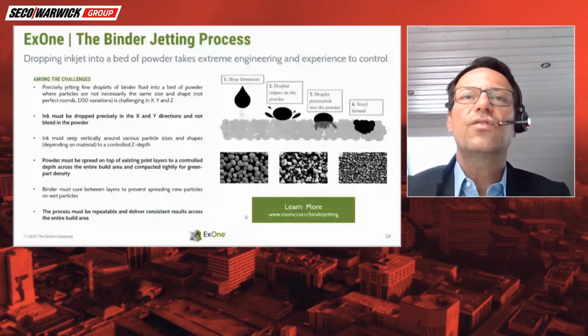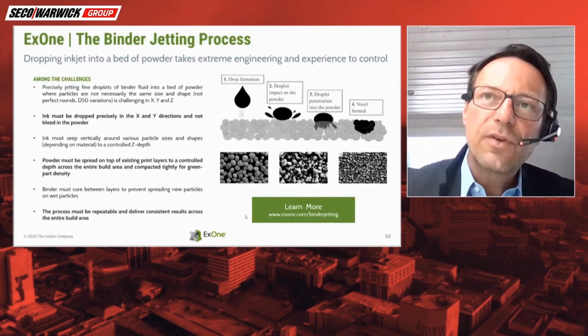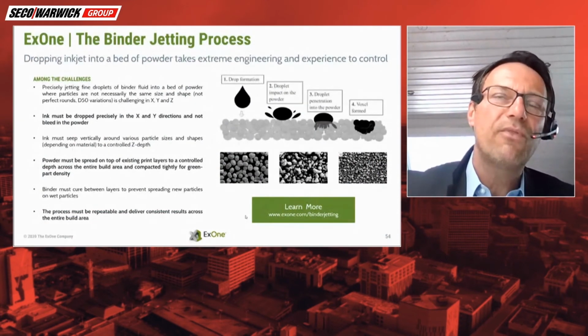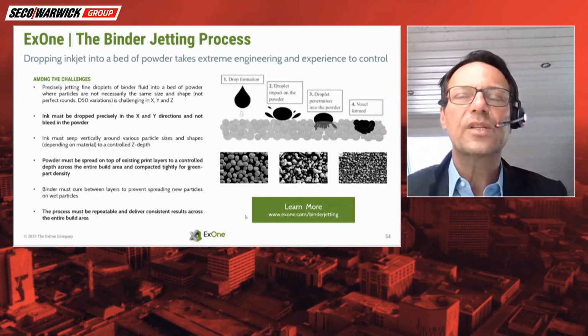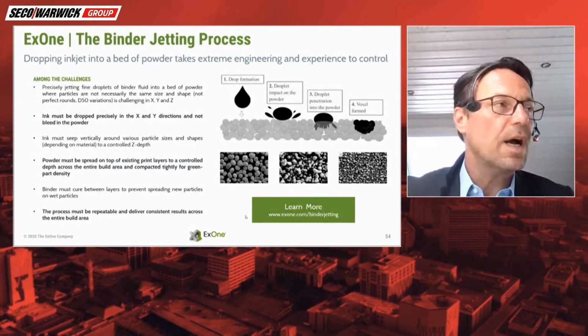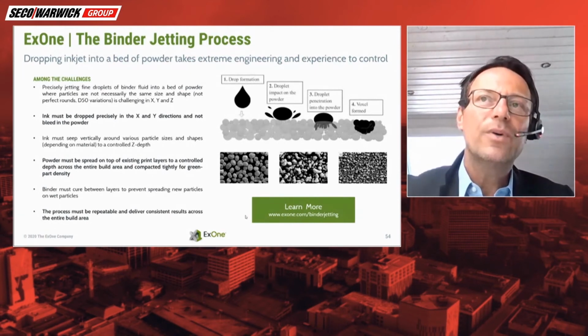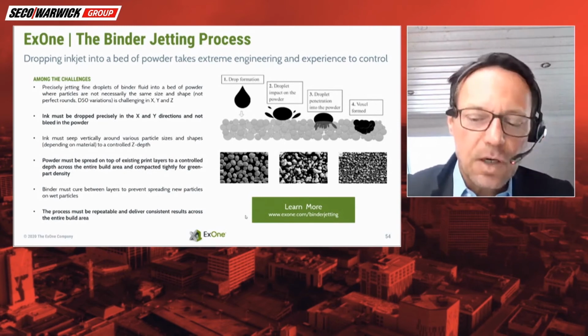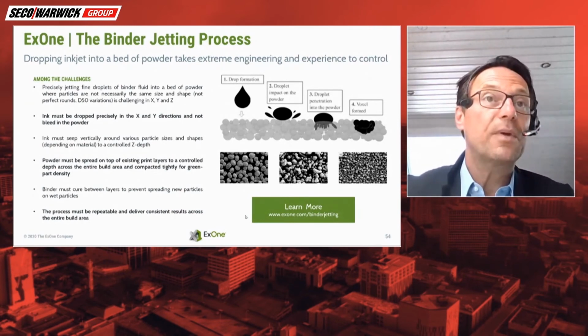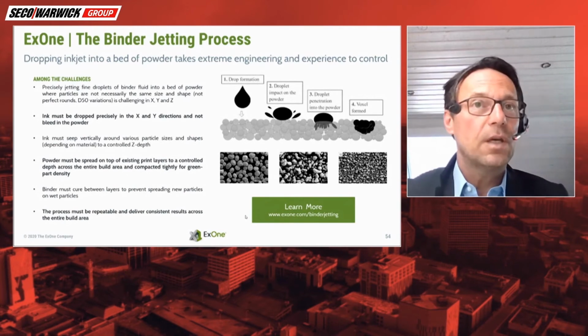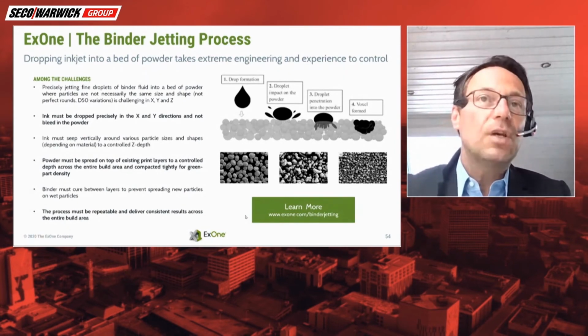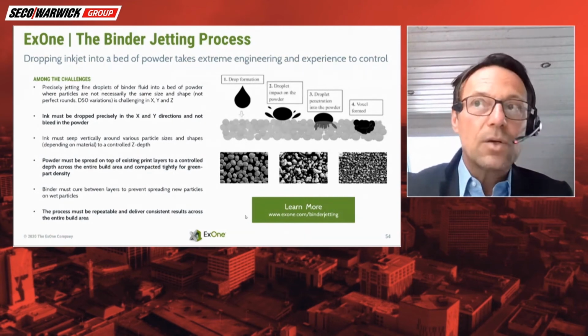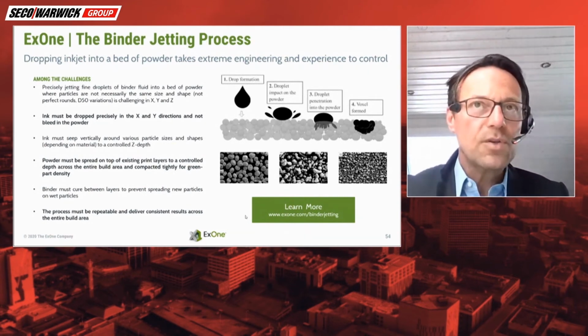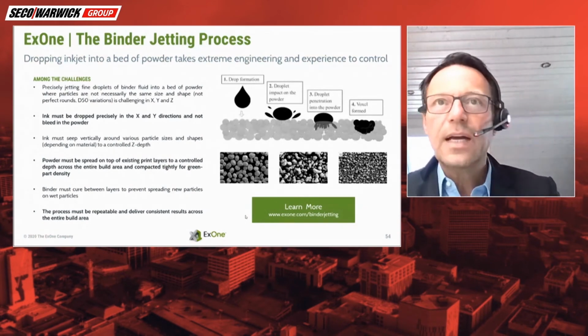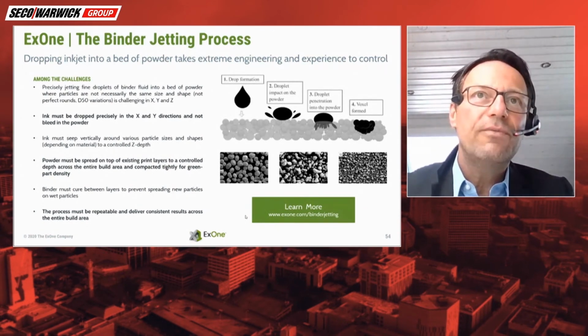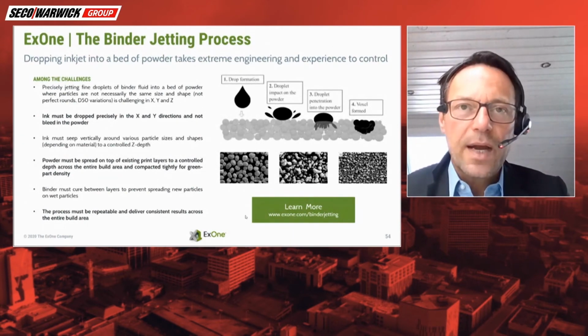It sounds very simple, but sometimes it's not as simple when you go through the process. There's the drop formation, so how the firing of the printhead works, how big the droplet is, and how it hits the surface of the powder and starts to penetrate. You want it to penetrate only as deep as you want. So in the Z direction, we don't want it to bleed out. The same goes for left and right: we want to form a voxel and not bleed out. This is the difficulty of doing binder jetting in the right way.